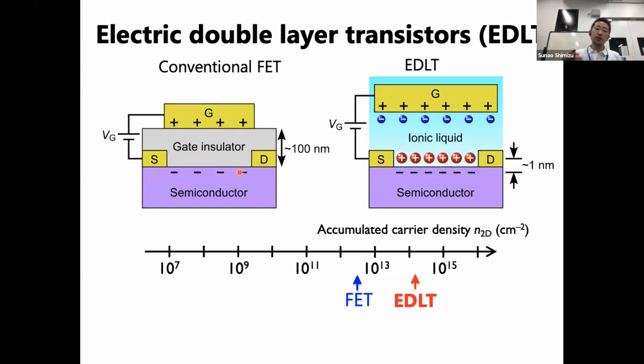But what happens when we change this solid gate insulator to liquid? The answer is very simple. When we apply gate voltage between the gate electrode and the semiconductor, we observe the formation of the electric double layer on the surface, and due to the high capacitance of the electric double layer, we can accumulate a very large amount of charge carriers on the surface of the semiconductor.